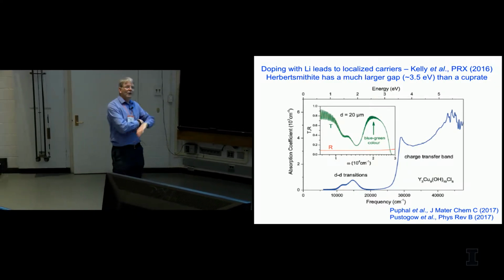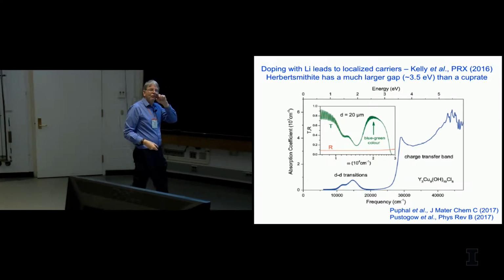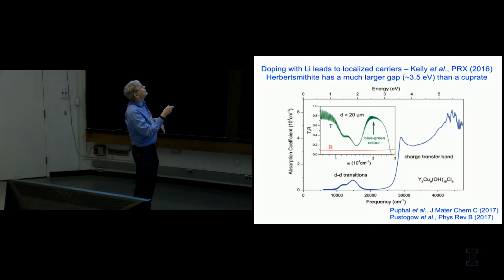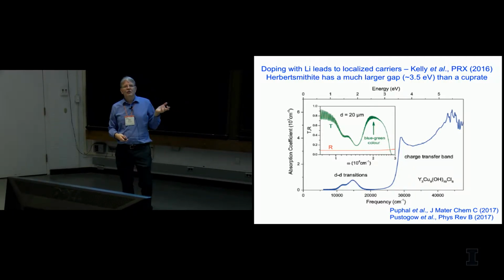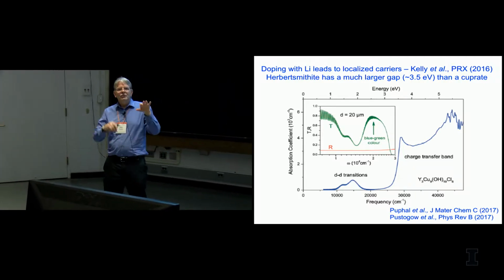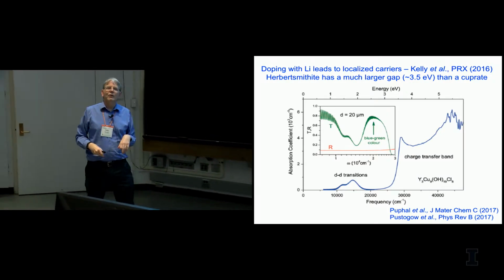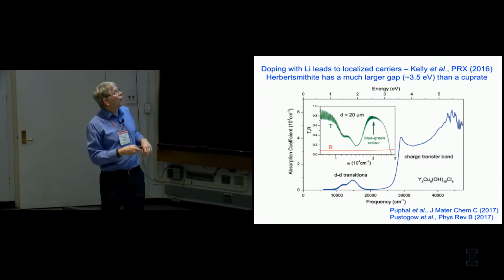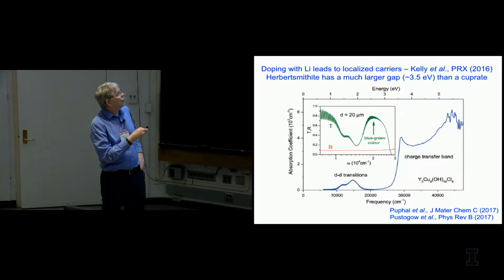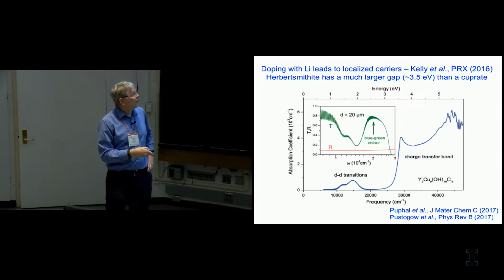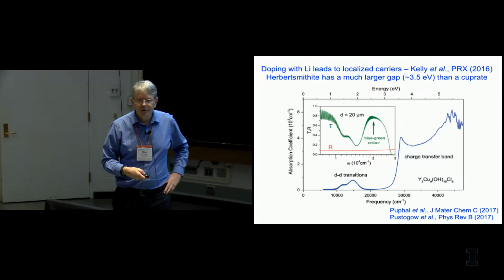And so this is a problem I said before. Cuprates are sort of an island of stability where the doped holes are mobile. Simply replacing oxygen in this case by hydroxides changes the degeneracy between the copper and anions in such a way that you get polaron formation. If you look at the band gap in the material, it's about 3.5 electron volts, so it's more comparable to nickel oxide than it is, say, to a typical cuprate.